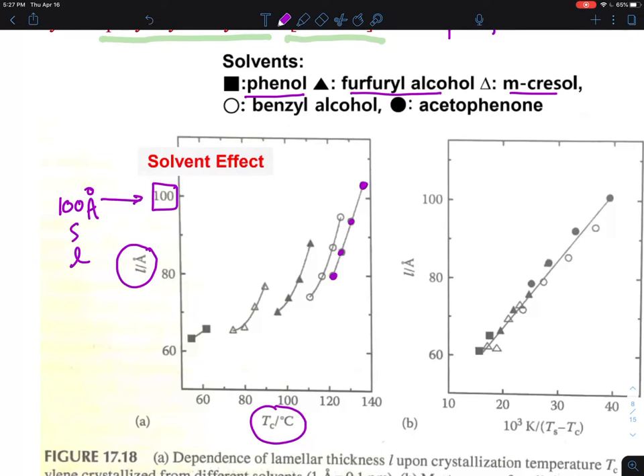When you go to higher crystallization temperature like here, then you will have a chance to develop slow, well-developed crystals. The chain has enough time to form the packed structures. And so therefore the thicknesses are essentially pretty much well-matured and thicker crystals.